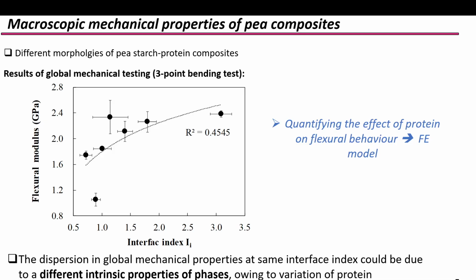There is also some dispersion in the global mechanical behaviors at the same interface index, which can be related to the variability of the intrinsic properties of the phases, but also to the degree of transformation at SME level. So in order to further quantify the effect of the protein on the flexural behavior, we used finite element computation at the macroscopic scale.